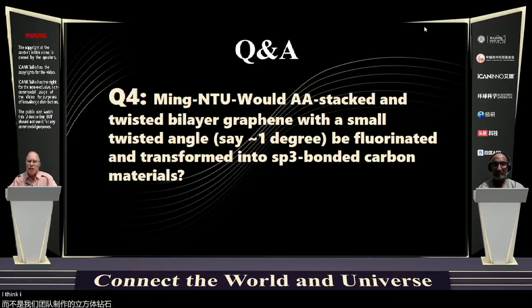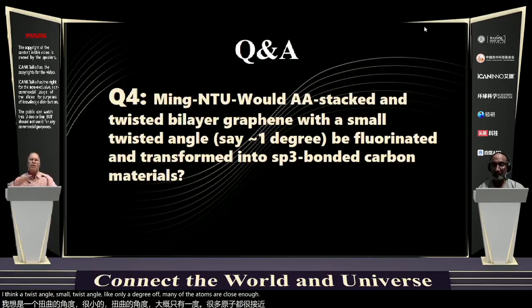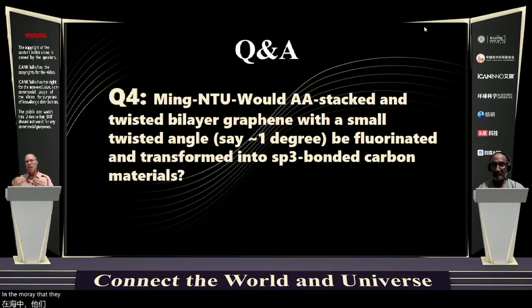I think with a small twist angle, like only a degree off, many of the atoms are close enough in the moiré that they would be able to bond with each other. And some sliding might happen as a consequence of favoring that bond formation and favoring achieving perfect sp3 bonding, which might eliminate the 1 degree misfit or twist that we started with. So those are really good questions.